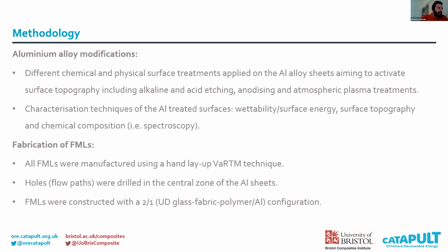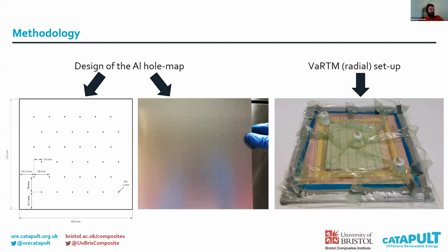Fabrication of the FMLs was carried out using a hand layup VARTM technique. Holes, or flow paths, were drilled in the central zone of the aluminum sheets to allow resin to flow across the thickness of the preforms during infusion. And also the FMLs were constructed with a 2-to-1 configuration. Here you can see the design of the aluminum sheets used to manufacture these FMLs, and then on the right side, you can see the FML layup after infusion.